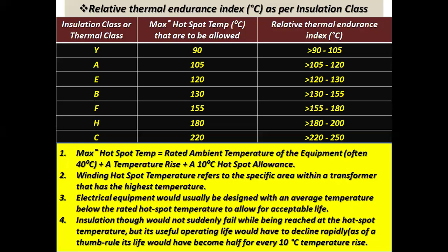Electrical equipment would usually be designed with an average temperature below the rated hotspot temperature to allow for acceptable life. Insulation, though, would not suddenly fail while reaching the hotspot temperature, but its usual operating life would decline rapidly. As a thumb rule, its life would become half for every 10 degrees centigrade temperature rise. Most important to note.